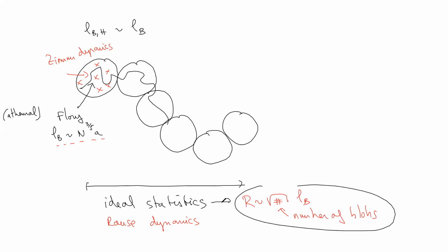And the Rouse dynamics, because now you have a collection of blobs that are independent from each other. So when this flows at a certain velocity in a fluid, each of those rigid-like units will contribute independently of the other. So you are really summing the number of objects that have all a 6 pi eta l_B drag coefficient. Okay, that's the picture for the dynamics